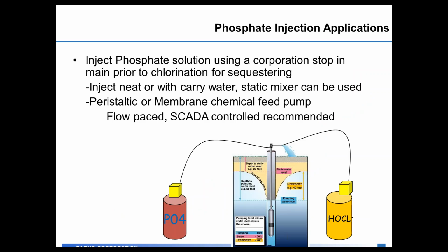When we talk about phosphate injection applications, we typically inject phosphate solution with a corporation stop in the main prior to chlorination. This is especially important if you're using the phosphate for sequestering of iron or manganese. You need to get the phosphate in first to sequester the iron and manganese before you add the chlorine, because chlorine will oxidize it and precipitate it out.